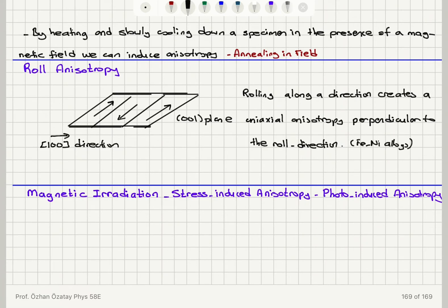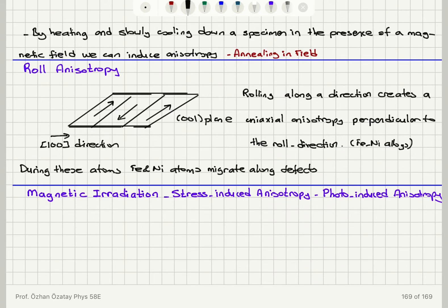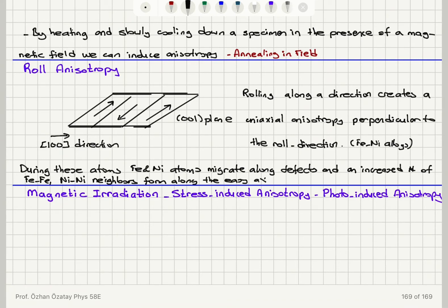This technique is used in iron-nickel alloys — permalloys. During the rolling treatment, atoms migrate along the defects introduced in the rolling process. An increased number of iron-iron and nickel-nickel neighbors form along the easy axis, and this produces the anisotropy.